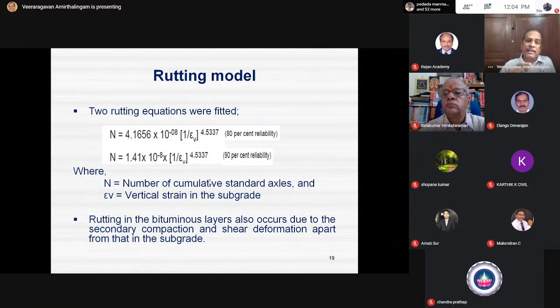You can find number of repetitions is related to the vertical compressive strain on the top of the subgrade. It also says rutting in the bituminous layer also occurs due to the secondary compaction and shear deformation apart from that of the subgrade. So you have a rutting 20 millimeter. What is the contribution of the bituminous mix? What is the contribution of the subgrade? This is something that one has to study. Whoever wants to do a research has to separate it out.